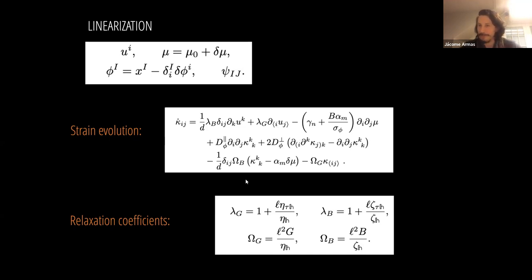But what is different here is that the plasticity effects relax the strain, as they should. So there is a relaxation coefficient here, omega_B, which is a bulk relaxation coefficient, and there is a shear relaxation coefficient here. So naturally, the plasticity out of equilibrium relaxes the strain. And so if you somehow deform the equilibrium state, it will permanently deform because the intrinsic metric will evolve in time such that the strain in the system will become zero at the end of the day because of this relaxation.